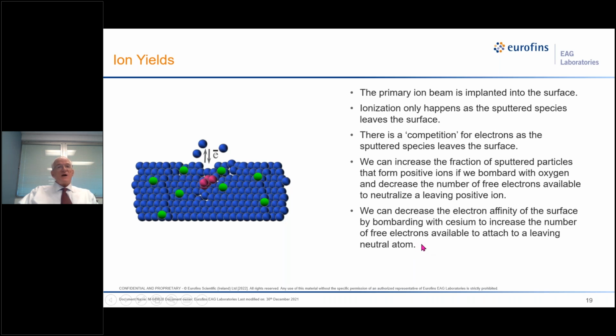And remember, there are lots more leaving atoms than there are ions. And these two, some would call them artifacts, are responsible for why we do SIMS in the first place, because these two processes increase the sensitivity of SIMS by between 3 and 4 orders of magnitude. Without this enhancement, say if we bombarded with argon, our sensitivity or detection limits would only be marginally better than those of XPS and Auger electron spectrometry. It's because of these enhancing bombarding species that it works. And again, that's another complication of SIMS. People ask, why is it so complicated? Because you have to decide whether to bombard with cesium or oxygen and what kind of ions to detect. It requires a lot of experience to determine how to do this the best.